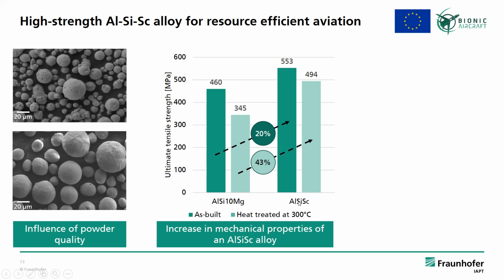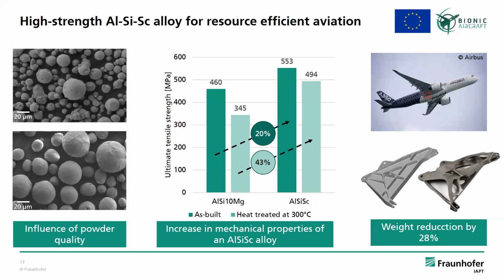And I want to give you the example also from the bionic aircraft project here, where we performed a material development for an aluminium silicon scandium alloy, leading to ultimate tensile strength of 553 megapascal in the as-built state, and in the heat-treated state 494 megapascal. And the ductility in this case was around 5 to 6%, which is quite okay, I would say, for a silicon scandium based material. And in the end, we came to these topology optimized demonstrators that I have shown you previously already.